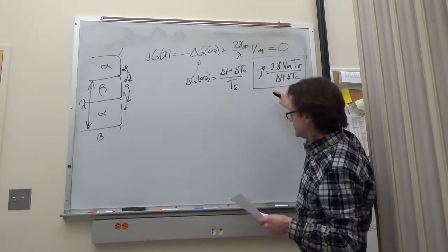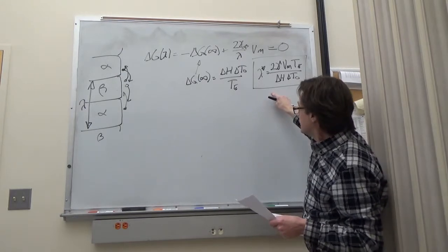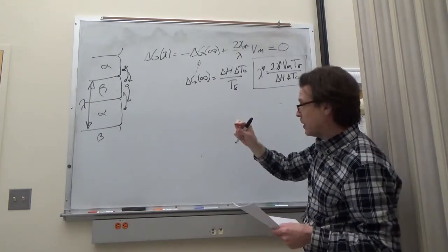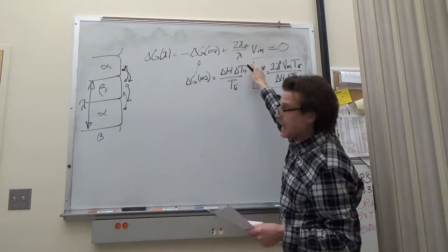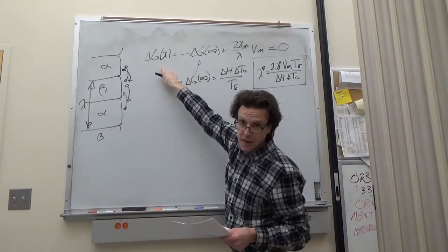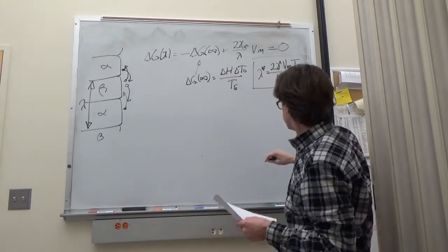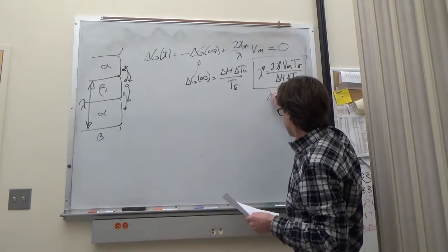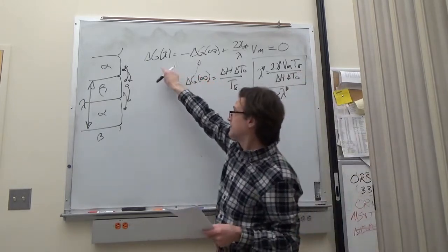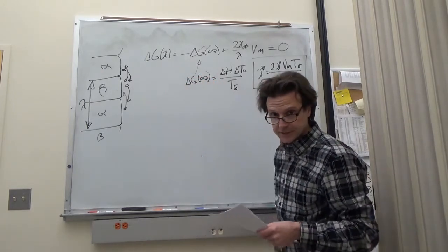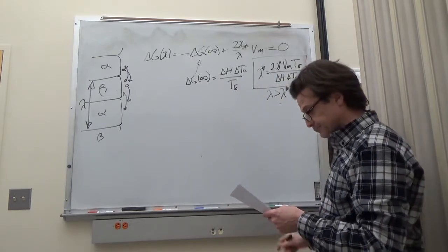And basically, this is showing that when lambda gets too small, that means that we've created so much surface energy that we stop having any thermodynamic driving force. So lambda must be greater than lambda star if we're going to have a driving force that's pushing us to solidify.